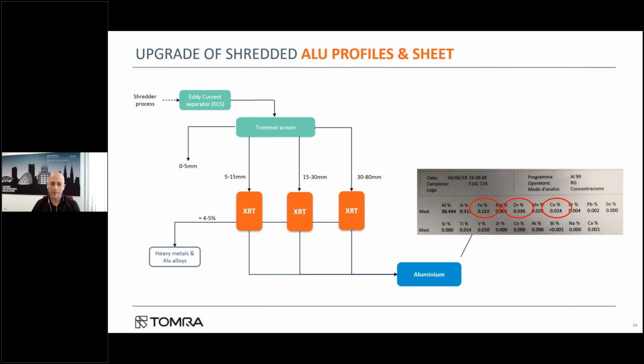They remelt the scrap into billets of 6060 alloys in this case, which are then used in their extrusion plant to make new profiles. The melt analysis of this final product, which consists of around 85% of this post-consumer aluminium scrap, shows that the content of zinc and copper is around 0.02 to 0.04%, with the iron content being around 0.2%.